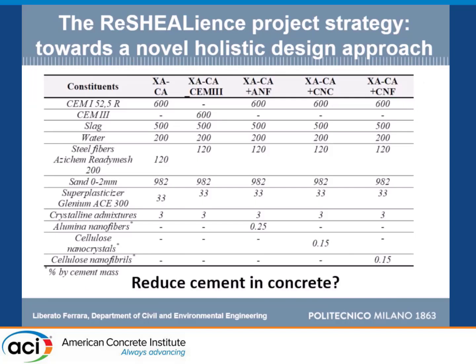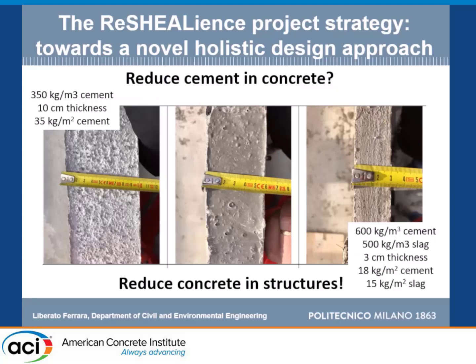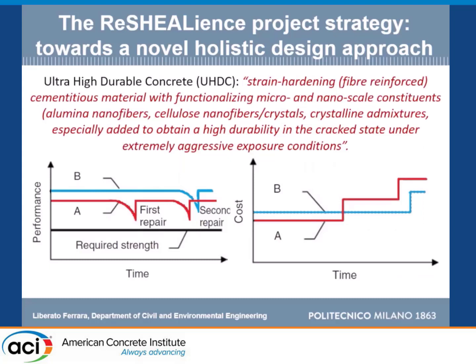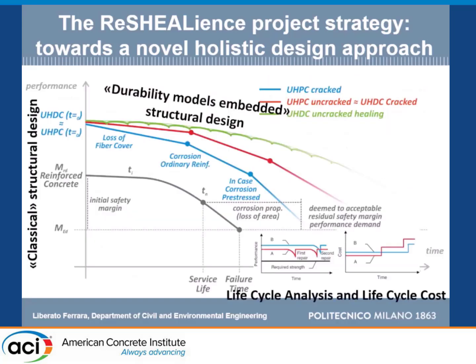So when you look at reducing cement in concrete and look at the mix design, say with 600 kilos per cubic meter of cement, you have not reduced the cement in concrete. But if you look at the square meter of wall, you go from an ordinary concrete at 35 kilos per square meter to our solution, which is just 18 kilos per square meter. So obviously we have different solutions, different performance, different costs. The issue is that we must frame this into a life cycle perspective. This is the other way to look into that.